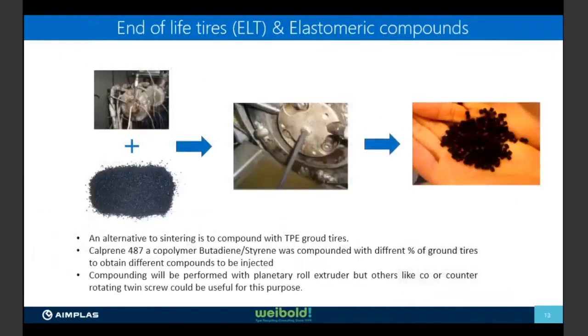Okay. One approach that is interesting is where we have ground rubber. We know that the rubber has very good properties in terms of toughness. So depending on the final product that we are going to obtain, we can introduce this ground rubber as filler in different compounds. Normally what we have is here on the left side, you can see the ground rubber that we obtained in some project. And what we did in that case is we mixed it, besides sintering, that we also sintered by hot plate press and different curing agents.